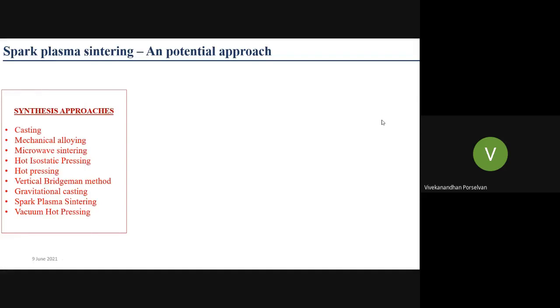And coming to the processing approaches, now we got some idea about why nanostructure is very, very important, why the nanoscale retention is very, very important. Because synthesizing a nanopowder is a very easy process. However, retaining it during the sintering process, that is converting your powder into the bulk form, which is a rigid form, which is so helpful in making the functional components, is quite challenging, because grain growth is an unavoidable phenomenon during the sintering process.